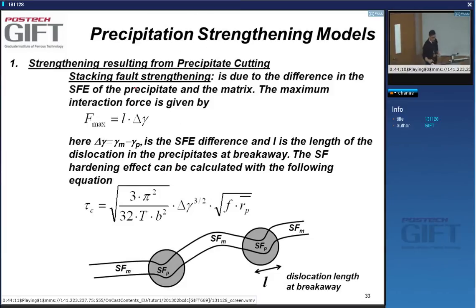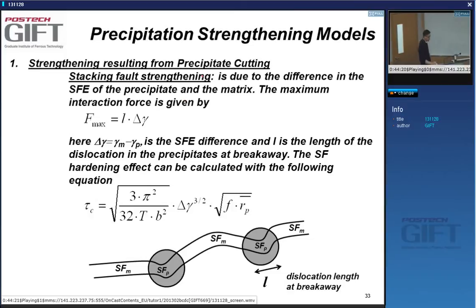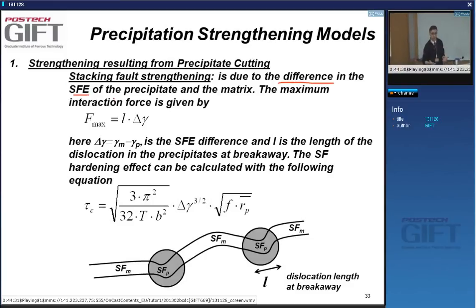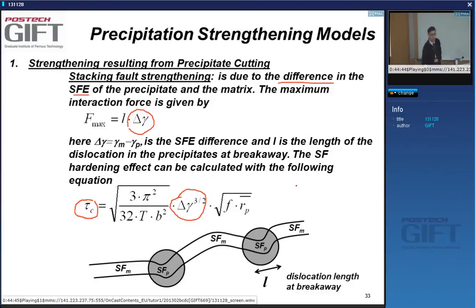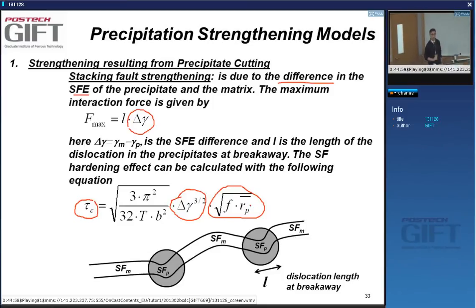Another strengthening mechanism takes into account that in certain alloy systems with low stacking fault energies, we have dissociated dislocations. Stacking fault strengthening is due to the difference in stacking fault energy between precipitate and matrix. The maximum interaction force is proportional to this difference, so the strengthening effect is proportional to the stacking fault energy difference to the power three-halves, and proportional to the square root of volume fraction times particle radius.